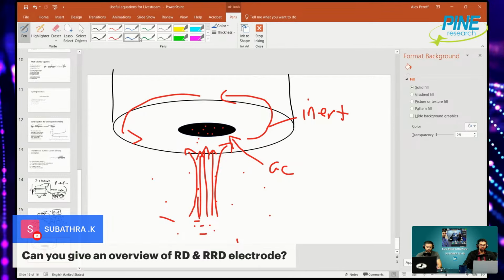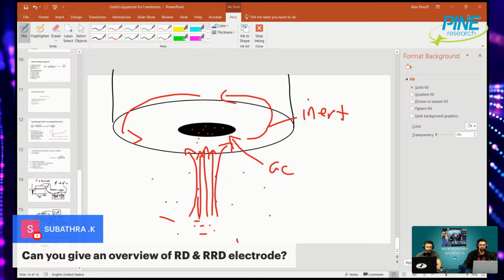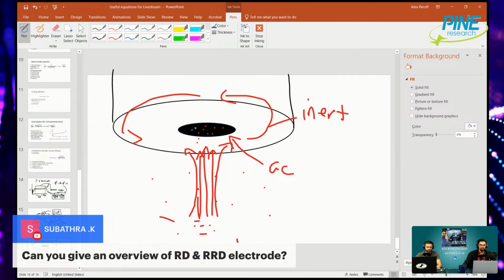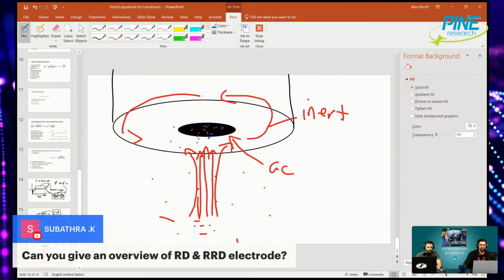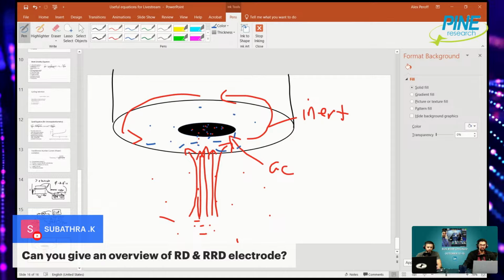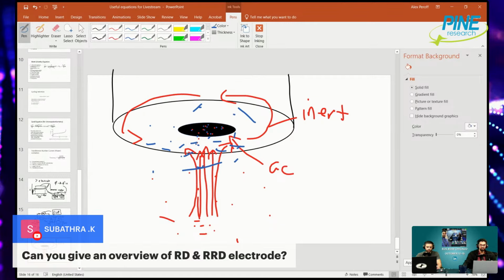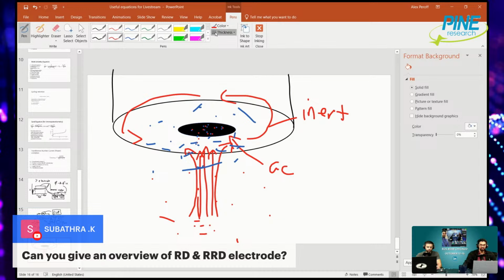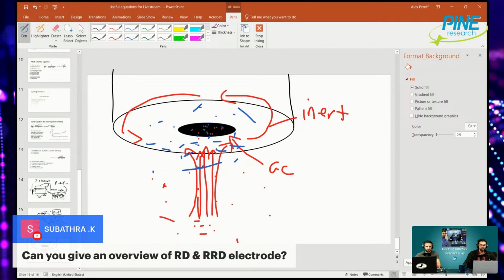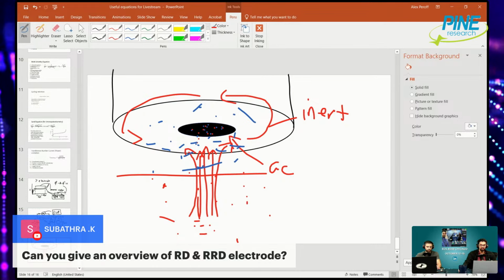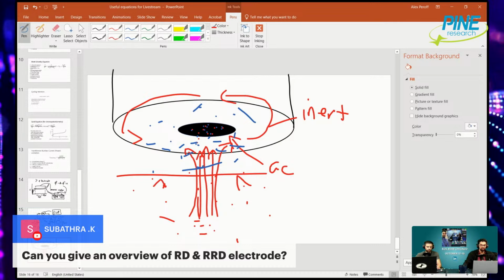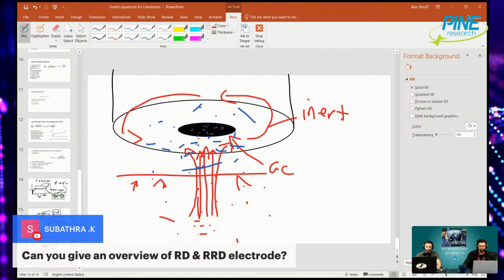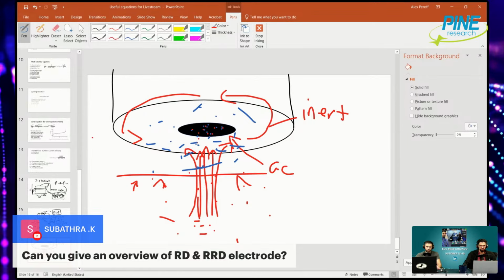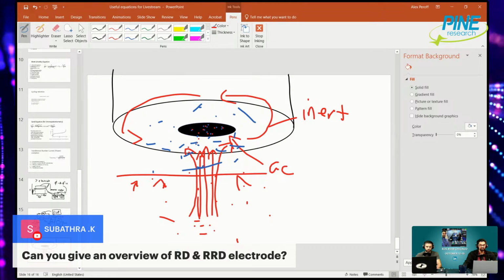Now, the nice thing about a rotating disc electrode versus a stationary electrode is that in a stationary electrode, you end up getting this diffusion layer. And any of the reduced species get oxidized and they just kind of stick around. They're near the electrode surface. And you have to move much further away from the electrode for new molecules to get close to the electrode.